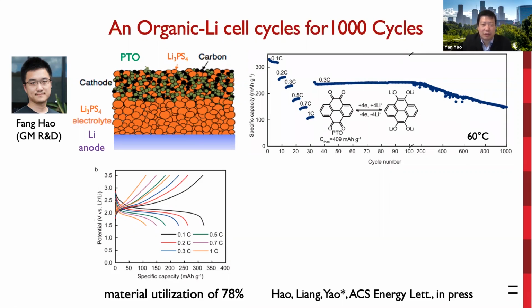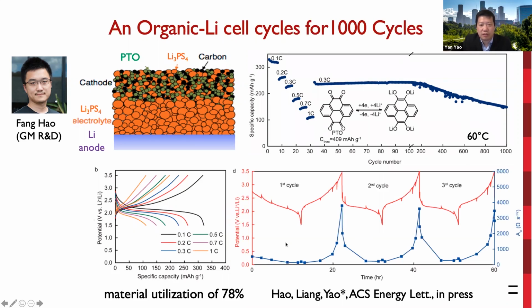To understand the stability, the evolution of the cathode electrolyte interface was probed by in-situ electrochemical impedance. The Warburg coefficient, AW, can be extracted from the electrochemical impedance spectra, which reflects ion diffusion resistance at the cathode electrolyte interface. What we see here is that AW remains low during the majority of the cycle, but increases sharply when the voltage exceeds 2.9 volts versus lithium, at which potential oxidation of the electrolyte is expected. Upon discharge, AW quickly reverts to a lower value and remains so until charging to the high potential in the next cycle.